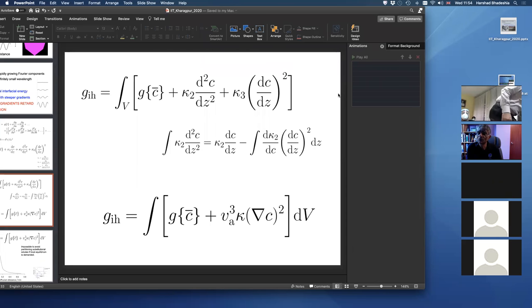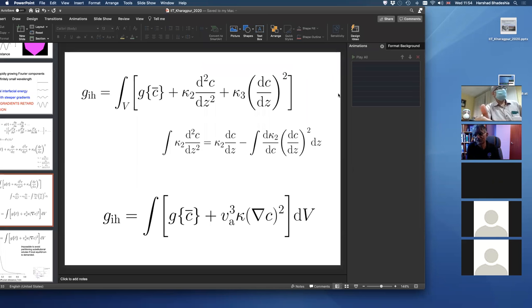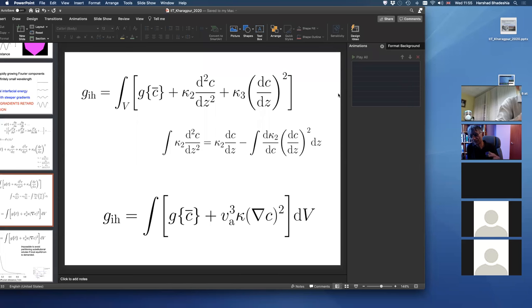On whether local liberation of heat matters: probably not unless the transformation rate is very high — for example, in martensitic transformation at sub-zero temperatures, the recalescence does alter how the interface moves. But rates of transformation at high temperature are too small for individual interfaces to be significantly affected. If dealing with a very large chunk of material, you get a peak in temperature in the cooling curve from the collective effect of all transformations — but that is a macroscopic collective effect.